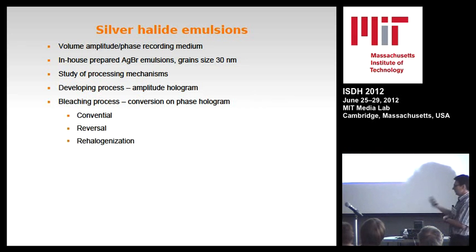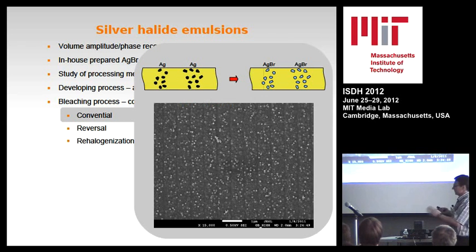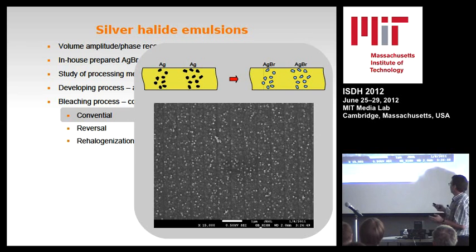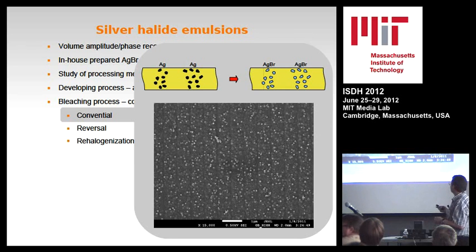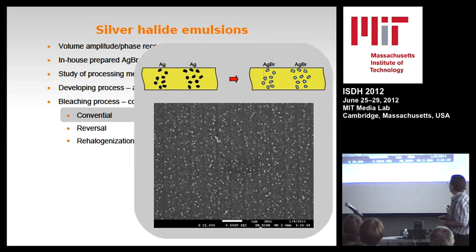When the developed material is bleached to form a phase hologram, several techniques can be used. The first two — conventional and reverse bleaching — are old fashioned. Today, mainly the rehalogenization process is used. I will show SEM images of conventional bleaching and reverse bleaching. In both cases you can see stripes in the medium, which means that some material was completely removed from the layer.